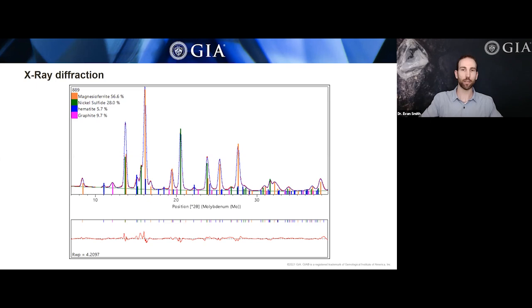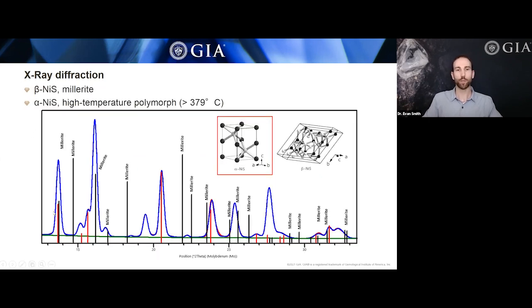And we'll just pull that out on this next slide here. So this is the same diffraction pattern we were looking at. And now we've just marked on here 2 different nickel sulfides. One is beta nickel sulfide, which is a mineral called millerite, and the other is alpha nickel sulfide from this comparison database. We have an example of a diffraction pattern from a synthetic sample. And if you look at beta nickel sulfide in these black lines, we see that if it were present, it would be producing peaks at these black lines, and we see nothing here.